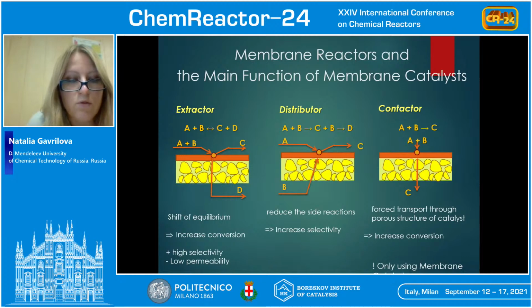Our work will be focused on using a membrane reactor contactor, and this type of reactor can be of greatest interest for high temperature reactions, which are characterized by the presence of diffusion limitation, as a result of which the degree of utilization of the catalyst surface is not significant. For many reactions, it's less than 5 or 10%. As an example of such a reaction, we will use the reaction of dry reforming of methane.